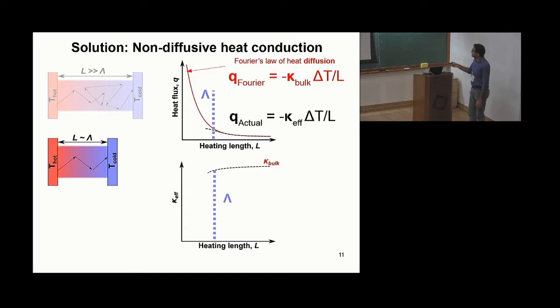Now delta T and L are fixed for both cases. Q actual is smaller than Q Fourier, so K effective that you measure will be smaller than the bulk thermal conductivity. And that's what you see here: as the length scale becomes smaller, the thermal conductivity starts dropping down.